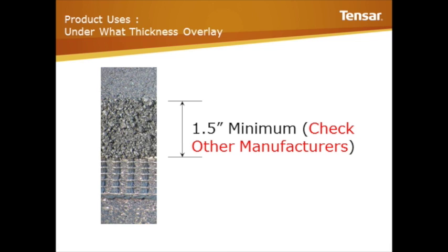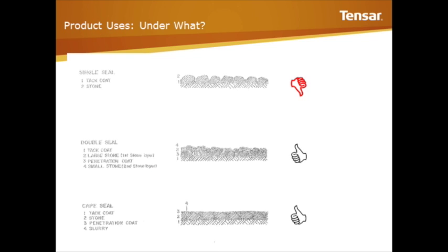Another question that's often asked, with all the Tensar products, our minimum thickness in all cases is 1.5 inches. I always recommend speaking with other manufacturers. For example, 2 inches is recommended on top of paving fabrics, and some other manufacturers may recommend that as well. Sometimes there are thickness constraints put on at intersections, for example, where there's a concern about the mix walking or shearing or flowing, however you want to reference it. And my suggestion is before you start playing with thickness, let's look at the project holistically. I wouldn't suggest that just increasing the thickness is going to solve your issue if your mix is walking on top of the interlayer. So other than that, typically you can get away with these minimum thicknesses in all other cases.